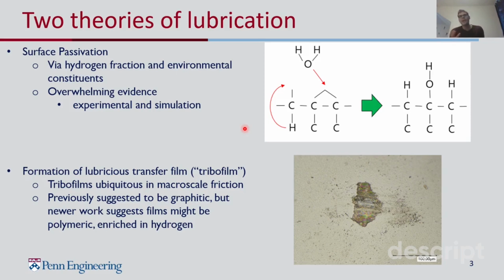But newer spectroscopic work suggests that these films might be polymeric based on the fact that they're heavily enriched in hydrogen and their density is quite low. So in fact, these might be polymeric in nature. The example I show on the right is actually a tribofilm from my macroscale sliding experiments.